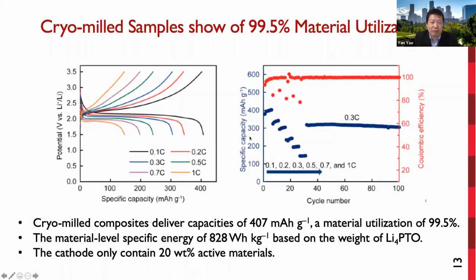Such significant reduction in the size of the active material contributes to the improved battery performance. Now the cryo-milled sample reached a capacity of over 400 milliamp hour per gram, which is a material utilization of over 99.5%. So this is the first time an organic electrode material accomplished full utilization in a ceramic electrolyte-based battery.